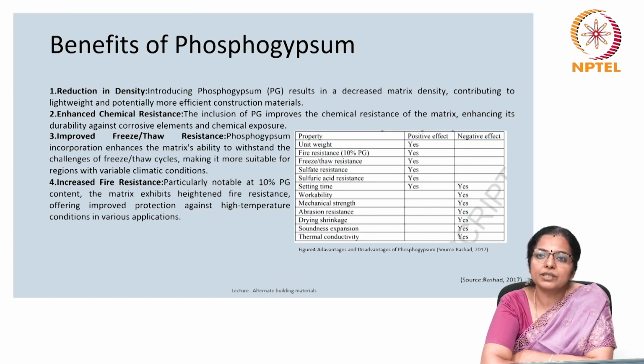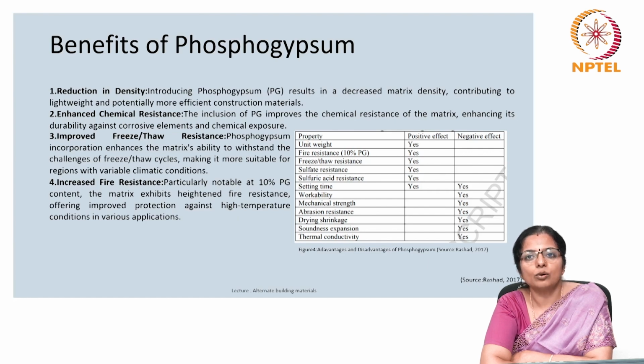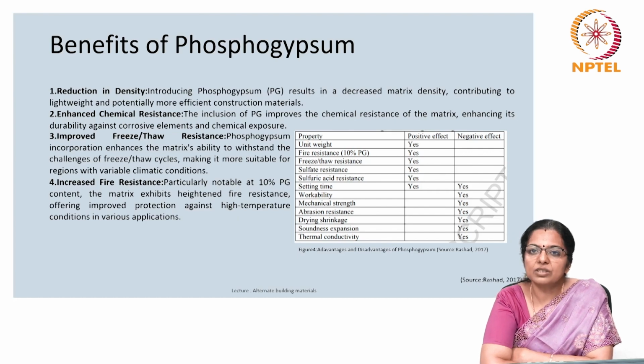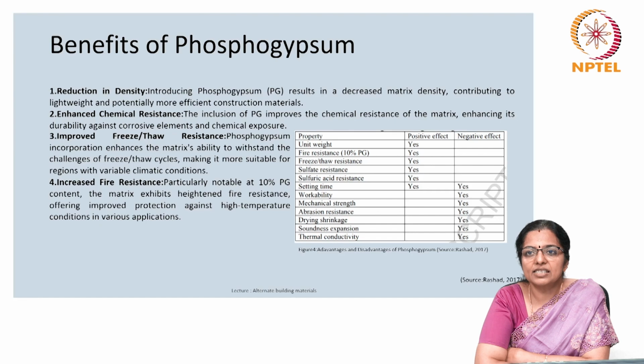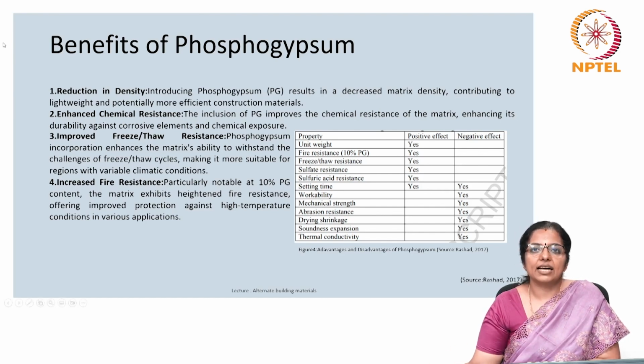Hence, adding phosphogypsum to construction materials has shown several benefits. It makes the material lighter by reducing its density, which can lead to more efficient construction. It can also enhance the material's ability to resist chemicals, making it more durable against corrosive elements. It improves the material's resistance to freezing and thawing, making it suitable for regions with very high diurnal variations. Finally, 10% phosphogypsum content in a material makes it more resistant to fire, providing better protection in high temperature conditions. Overall, using phosphogypsum can create construction materials that are lighter, more durable, weather resistant, and better at withstanding fires.